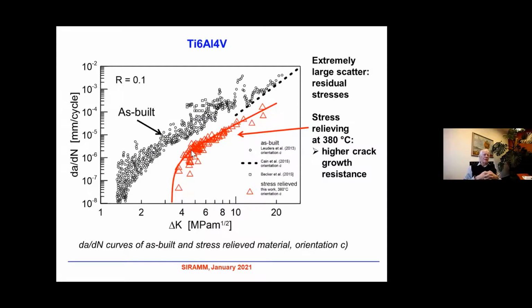Now let me compare this data with as-built material. Here you can see our data, but only orientation C in this case, after stress relieving at 380, and compared with as-built material. These data were taken from literature, from a paper by Leuders and a paper by Becker. You can see that their scatter was also very high. However, the curve for as-built material is shifted to the left. It means a higher crack growth rate. So for the same loading, let us say 6 megapascal meter to 1/2, the difference is nearly 1 order of magnitude or more. So here the propagation is much quicker.